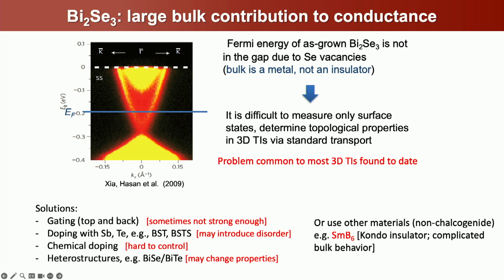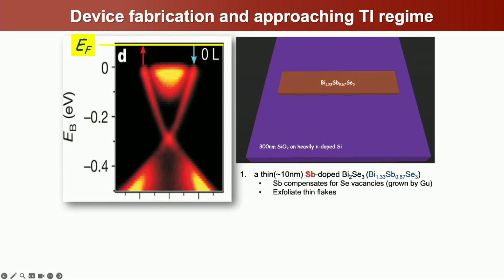So when we try to approach a Dirac point in these systems, we take a combined approach of basically two or three of the things I just mentioned to really try to get to the surface state only regime. We start with a thin flake of the material, and as was asked, why do we deal with a thin flake? Because we have less bulk in a thin flake. So we'll deal with something that's maybe 20 nanometers thick, where we hope the surface contributes at least as much as the bulk in a thin enough system.